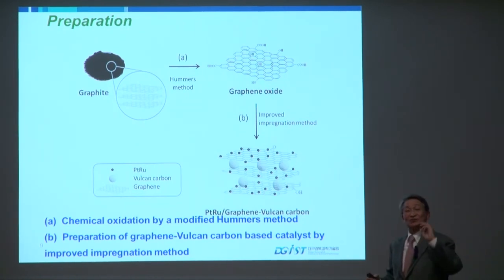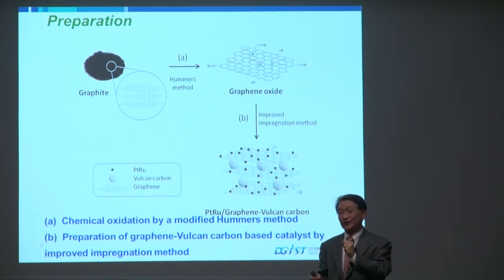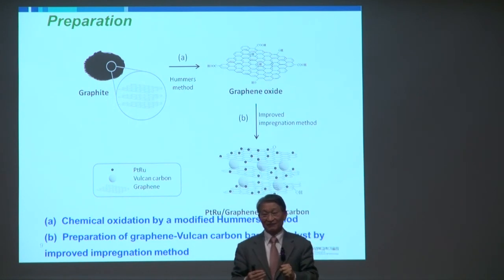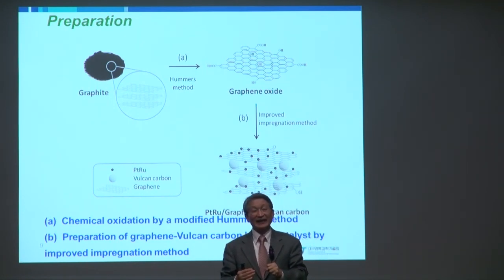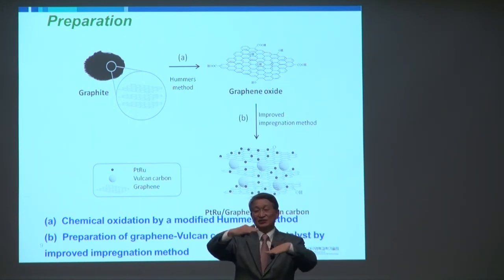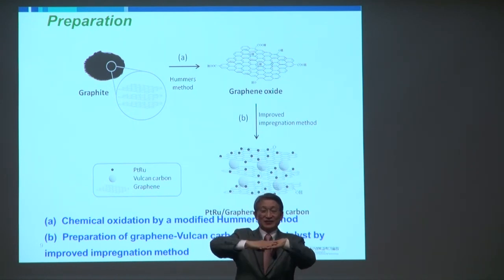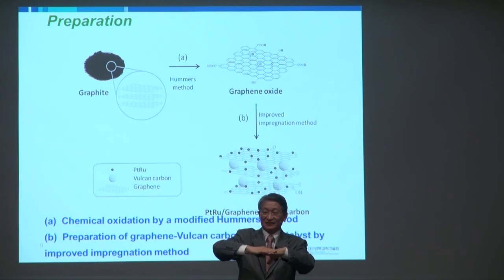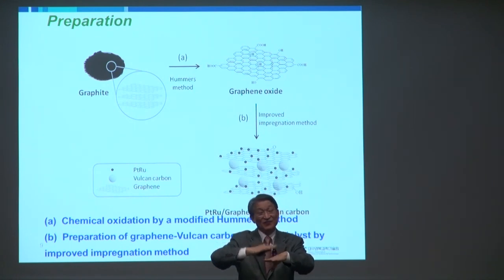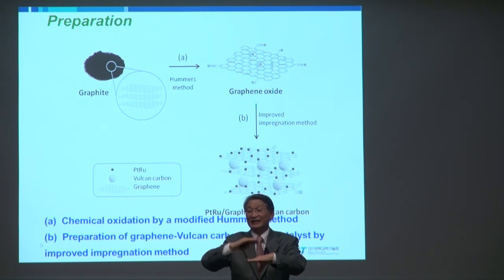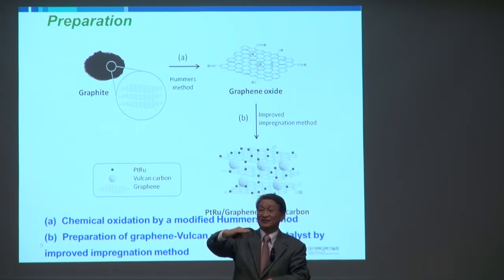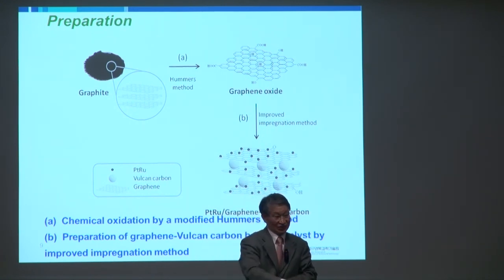Then, one of the main problems of graphene for fuel cell application is they are not staying as single layers, well separated singles. They tend to be stacked together. That means the surface area for the fuel cell application is not as much as the single graphene nanosheets.